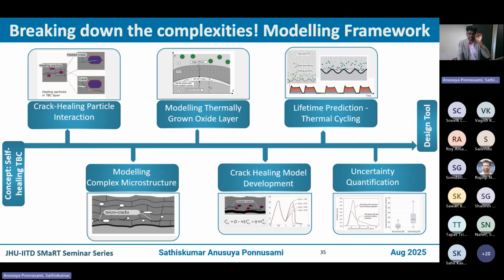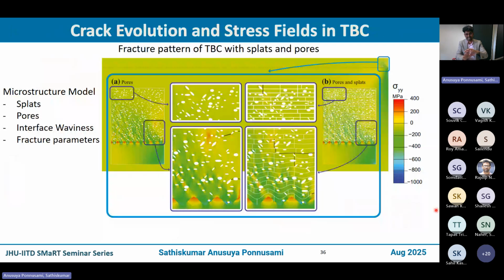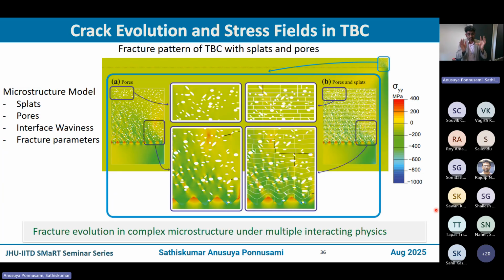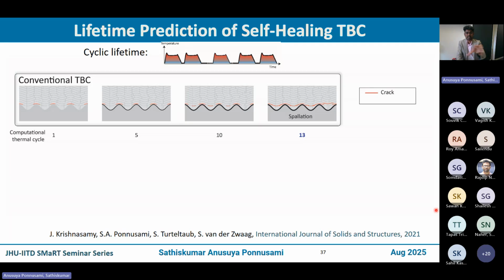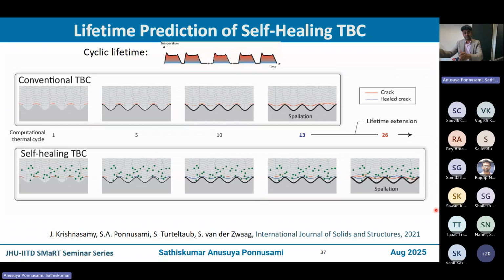Without getting into the details, I'm directly jumping to the result. There's one snapshot of the fracture simulation that we did, incorporating all the physics that you saw in the previous slide. Again, without getting into the details, what we get out of that is we can predict how many cycles you need to completely fracture the system, the coating. So that is your lifetime. For example, here without healing particles, the lifetime is 13 cycles, which in reality can correspond to 1,300 cycles. We did it in an accelerated manner. And if you put in healing particles, the number of cycles is quite high. So you clearly see there is a lifetime extension.